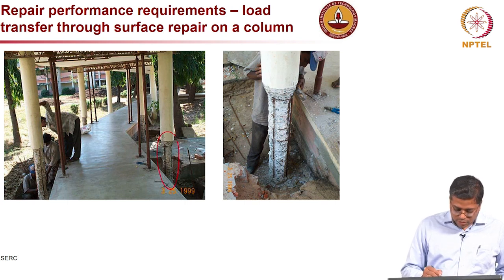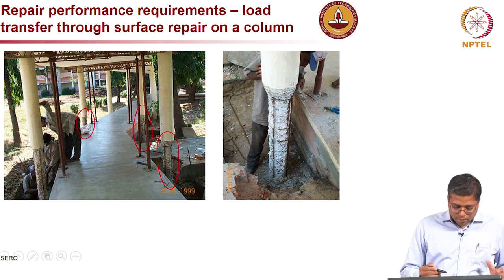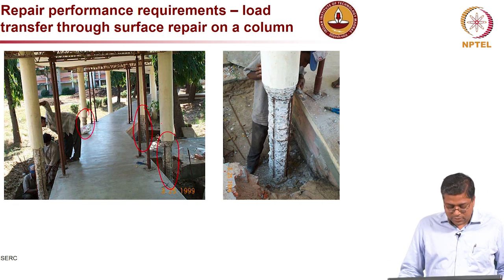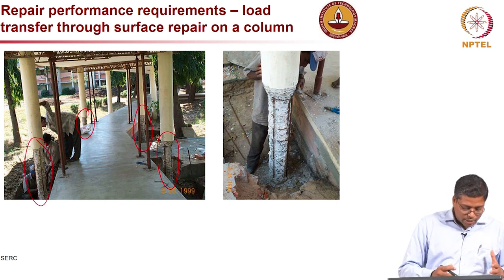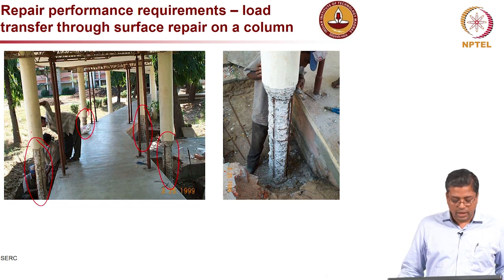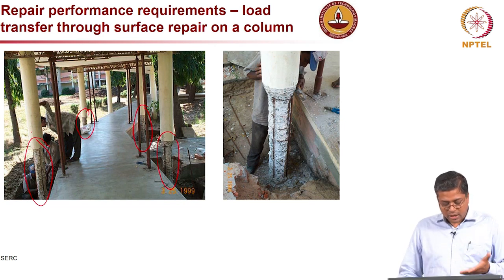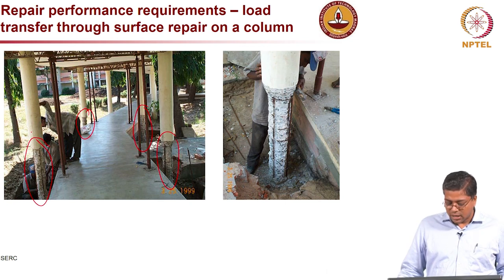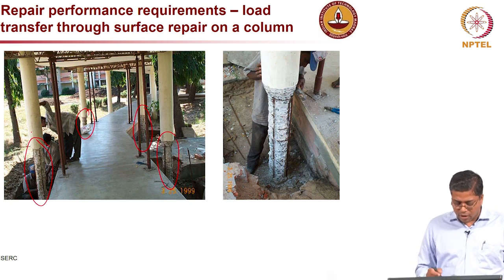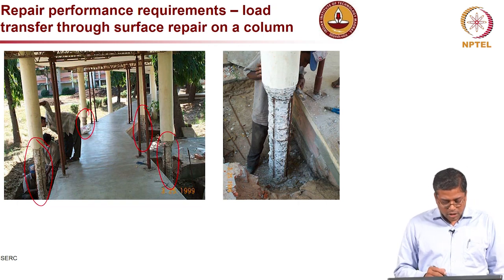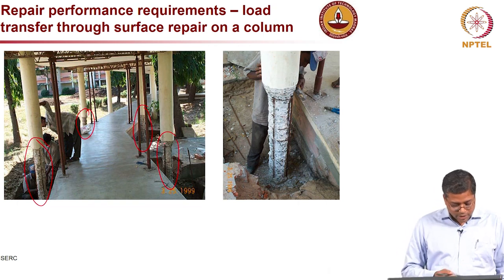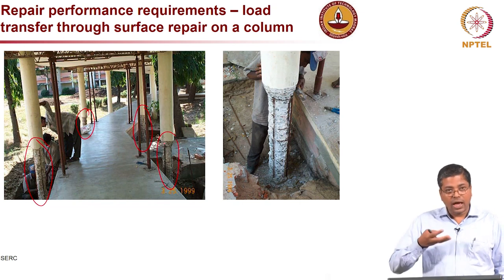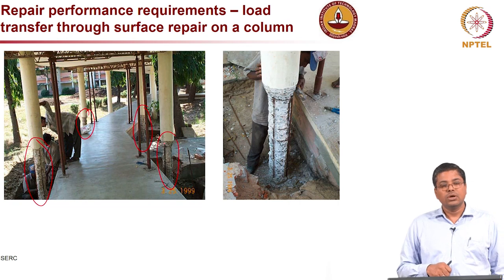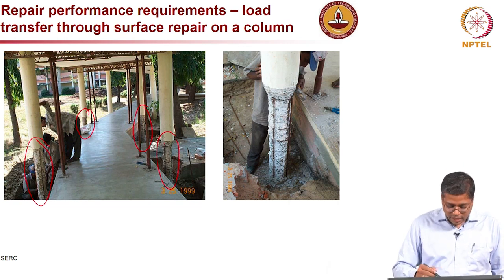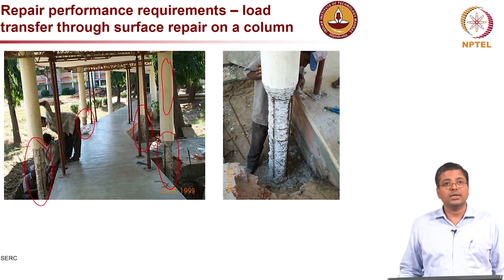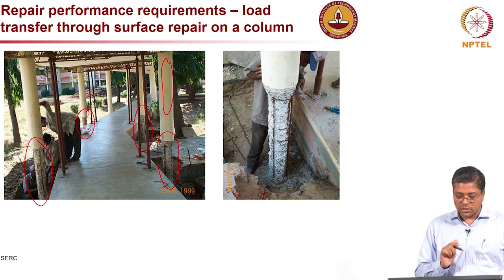You can see here most of the columns, probably there were a lot of capillary pores in this concrete, and that absorbed moisture from the ground during the rainy season. And then you can see very clearly about 1 meter height from the ground, the columns are all damaged, mainly because of the capillary suction of the moisture from the ground and maintaining it wet, and that leads to significant corrosion. Because why I am saying that this portion of the concrete is intact, it does not have any problem, so definitely moisture is the problem here.